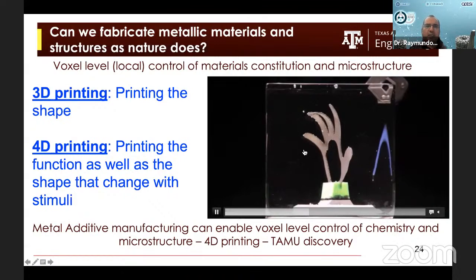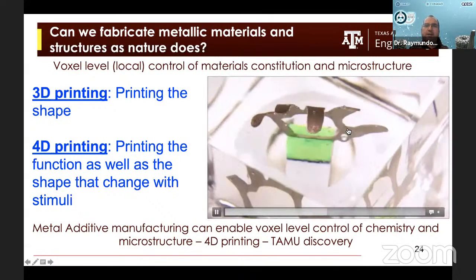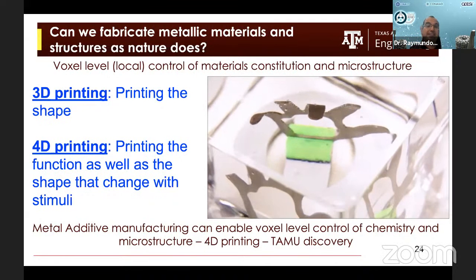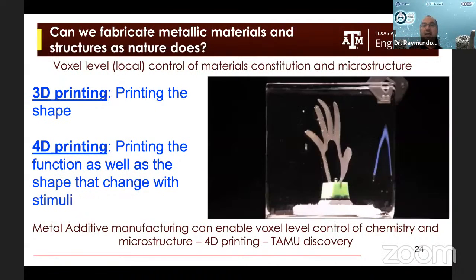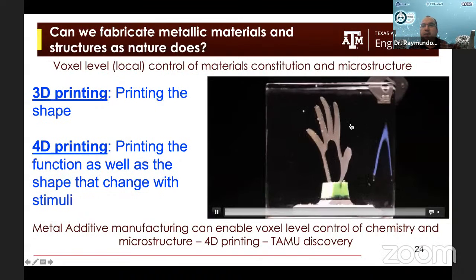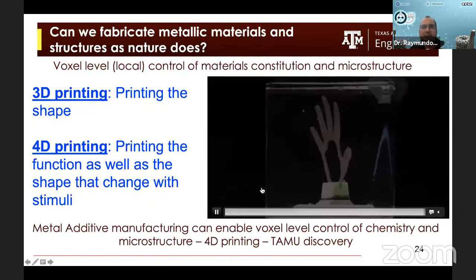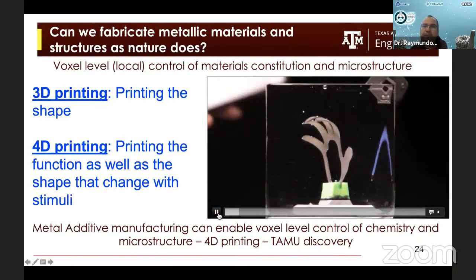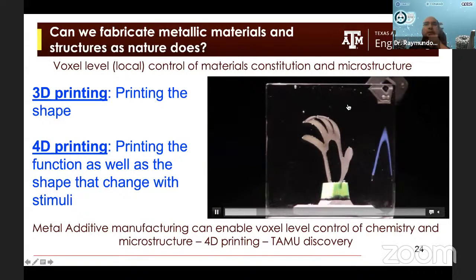This is a hand where every finger was printed with different process conditions. It was the same chemistry, so we didn't change the chemistry here. We just changed the processing conditions. And in this case, I think that the only thing that we changed was hatch spacing. So we used the same power and speed. The thing that we modified locally was, excuse me, hatch spacing. And we can see in this video how different fingers actuate at different temperatures.